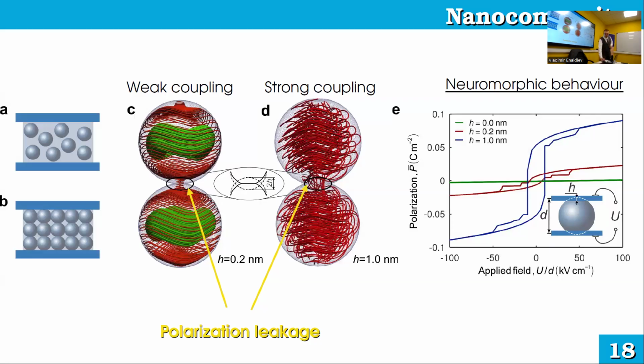And what is interesting, if you build a device that's presented here, so basically if we take a couple of particles and confine them between electrodes, we get very nice hysteresis loops. For example, when particles have no contact, you have this straight line. Okay, it's obvious. But the more contact they have, the more jump states you have on this hysteresis loop. And it's a good candidate for different neuromorphic applications where you need to distinguish between a number of different states in the object. Are the terms weak and strong coupling used here in the conventional sense? It's more like terminology, not super rigorous, just to take into account this spot and how lines go from one sphere to another.